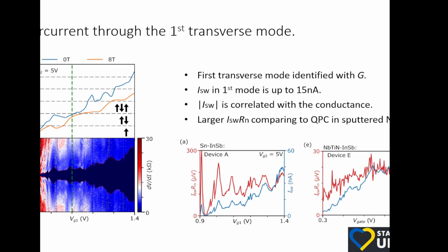And this is also, again, very unusual. It's the first time that I see this happen, where this kind of strong, clear signal of supercurrent exists in such a high resistance regime, with 13 kilo ohms of resistance in the junction. Usually it just gets suppressed. So you can see the quantized plateau, you measure supercurrent, and either it's not there, or it's very, very tiny and difficult to study, difficult to subject it to some additional field or gate and make something out of it. So I was quite pleased with these junctions.